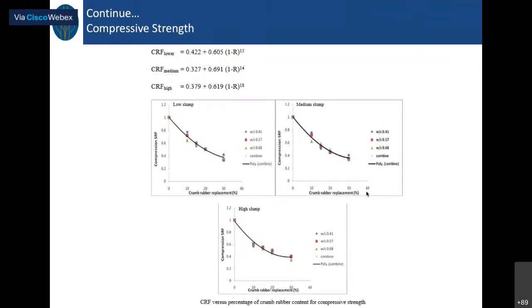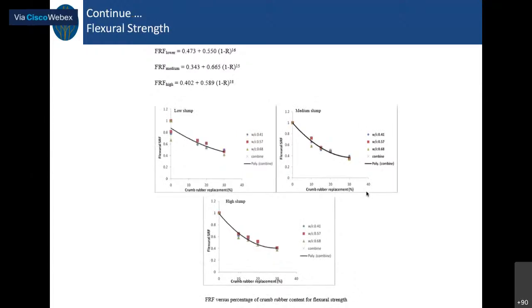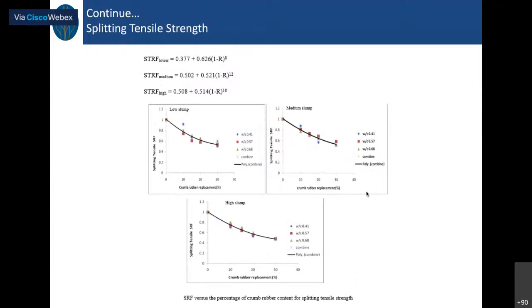So we introduced what we call reduction factors. We find the reduction factors, then we use the normal method of designing the concrete mix using ACI or the British code. After that, we multiply the target strength by the reduction factor, and then we find the real target strength of the rubbercrete. We have done this for the compressive strength, the flexural strength, and the splitting tensile strength.